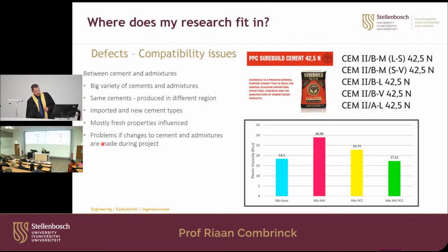So some of the work we've done here is, this is just a base mix, a normal Portland cement mix, and this is the plastic viscosity. So this is how steep the mix is and how difficult it is to work with. If you add metakaolin to it, you can see the viscosity increase. It becomes more difficult to work with.